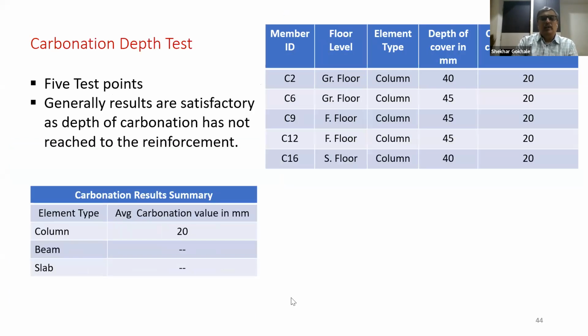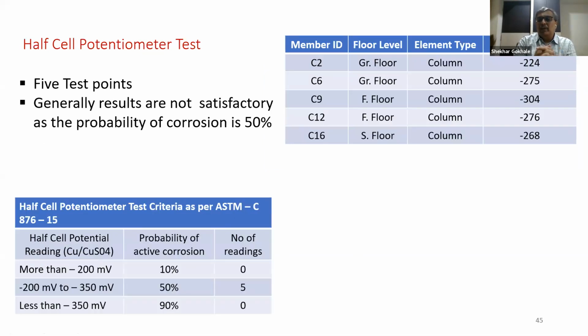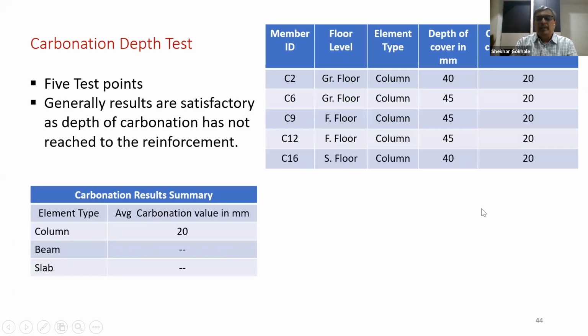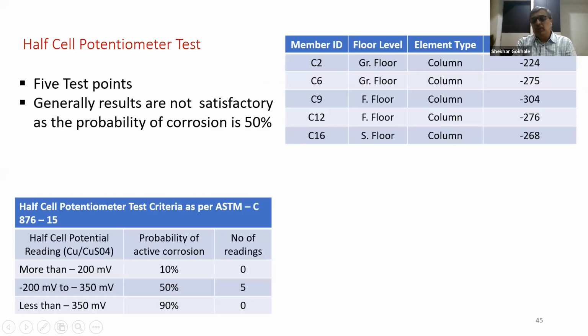Then we further carried out the carbonation depth test. The general cover of the column observed at site was around 40 to 45 mm, and the actual depth of carbonation is about 20 mm in all the 5 cases where we tested only columns. Then half cell potentiometer test, again we tested 5 columns. Out of 5 we got all 5 readings between -200 millivolt to -350 millivolt range. That indicates a probability of active corrosion of about 50%. So even though the carbonation depth is only 20 mm, there is a 50% possibility of active corrosion in the reinforcement.